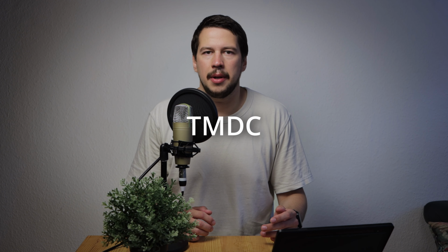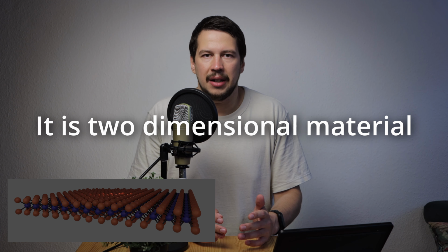It's called TMDC. The material is quite noticeable because it consists only of a few layers of atoms, and therefore it's called two-dimensional material. It means the electrons and holes in this material can propagate only within the sheet of material and cannot basically move within the direction where there are a few atoms. And even though the material is so thin, it is so optically active. From this very layer of atoms, you can get absorption of roughly 20%, which is basically blowing my mind.